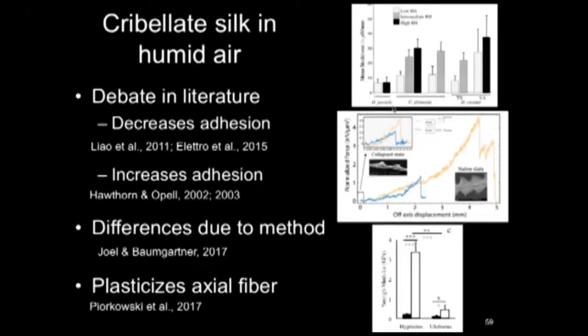A study that I had performed on 2 species of spider, we had found that compliance, so the stiffness, dramatically decreases in silks from wet fibers rather than from dry fibers. So we were inspired to think, well, given that the silks are not exposed to a wet glue or an underwater environment, we can control the plasticization of the fiber without artificially inducing it through those conditions that are pre-existing. So this is a perfect model for us to measure how mechanical plasticization impacts adhesion without coupling it with a previously confounding factor.